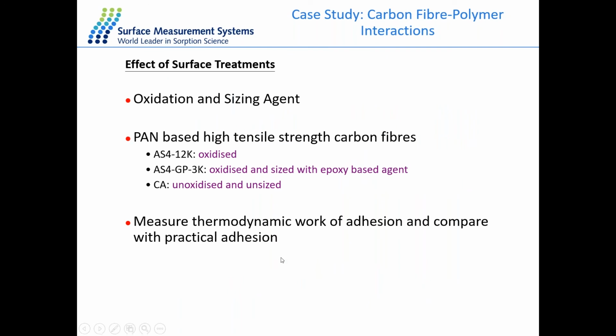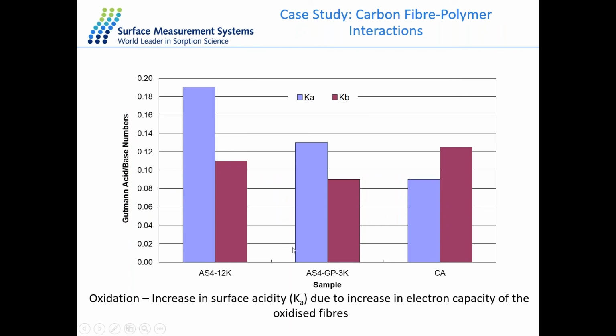We can also have a look at the effects of surface treatment. So an oxidized sample, oxidized and sized with epoxy agents, and comparing it to an unoxidized and unsized material. And this is the resulting Ka and Kb plots. What you can see is that due to oxidation, we have a higher Ka for our material. And this is, of course, what you would expect compared to our reference material. And our reference material has a much higher Kb, more electron donating groups on this sample here. And we can also see the effects of different types of oxidation as well.